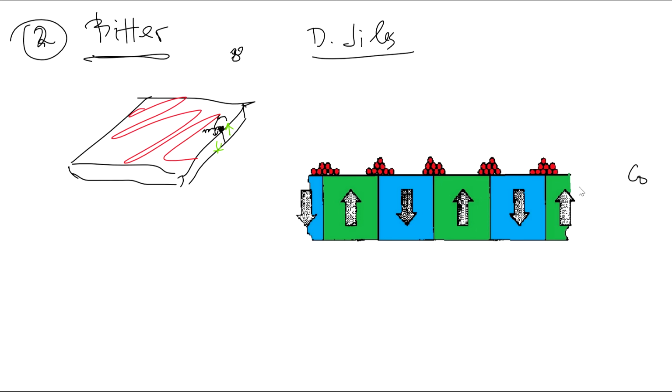and cobalt is typically used for magnetic recording. Magnetic recording is audio tapes, it is magnetic recording that's used in data storage, and that's actually nowadays used in computer hard disk drives. So if you take a cobalt film, and this is a cross section of the cobalt film, then areas of this material can be magnetized vertically either up or down, because it has an anisotropy axis. So this is the easy axis, as we learned from one of the previous lectures, vertical.